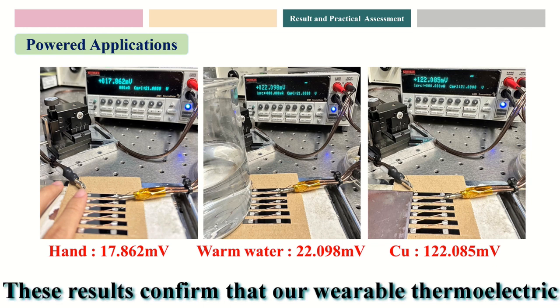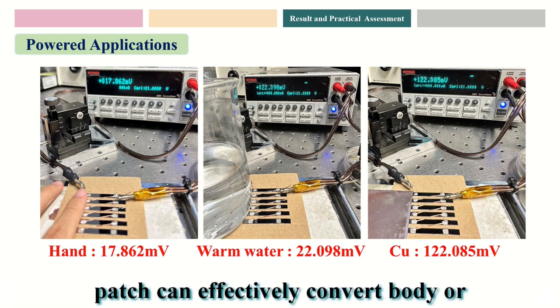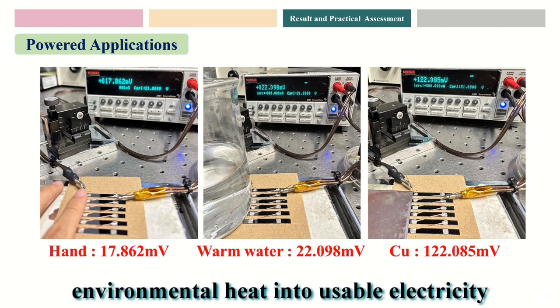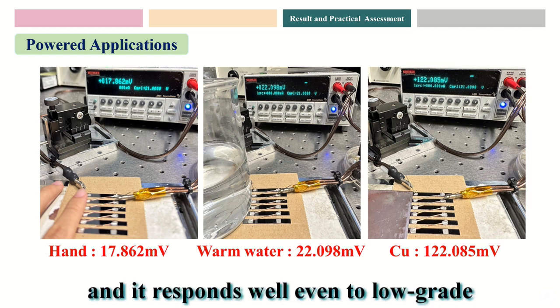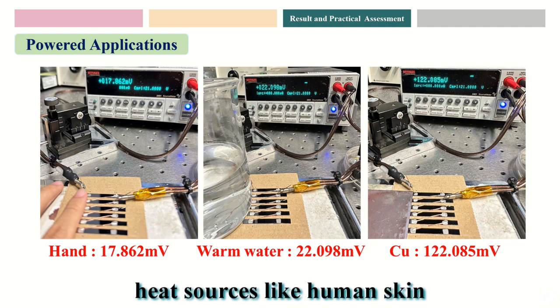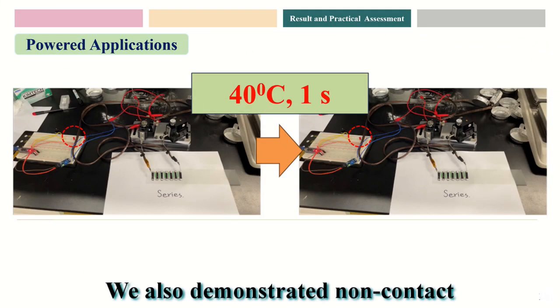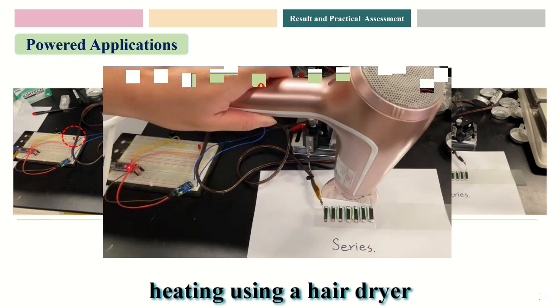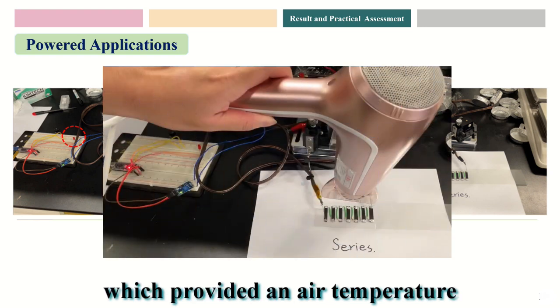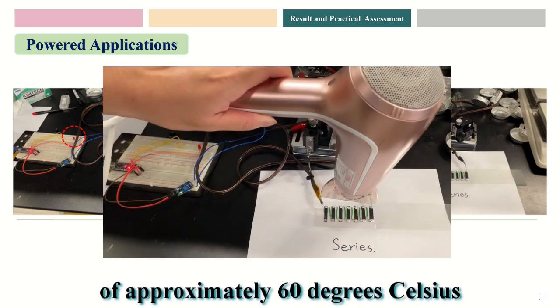These results confirm that our wearable thermoelectric patch can effectively convert body or environmental heat into usable electricity, and it responds well even to low-grade heat sources like human skin. We also demonstrated non-contact heating using a hairdryer, which provided an air temperature of approximately 60 degrees Celsius.